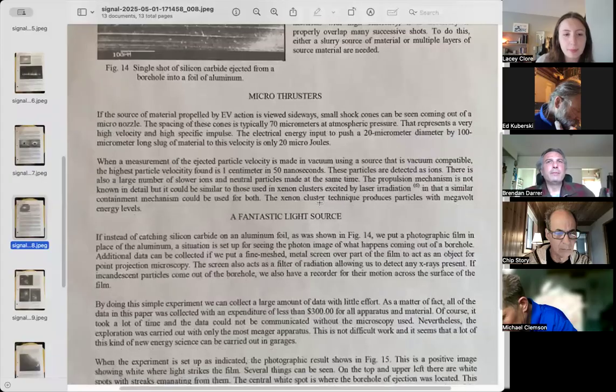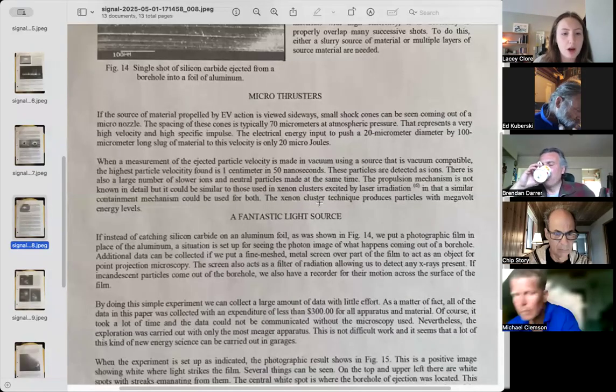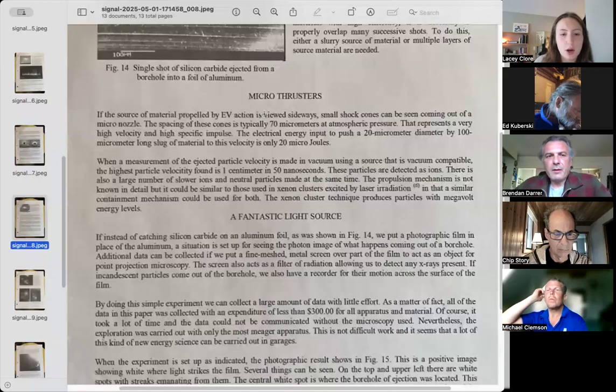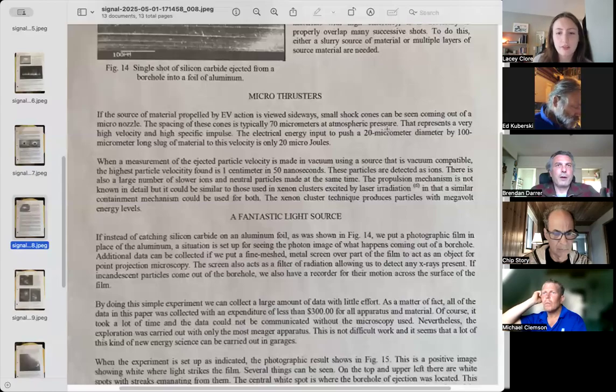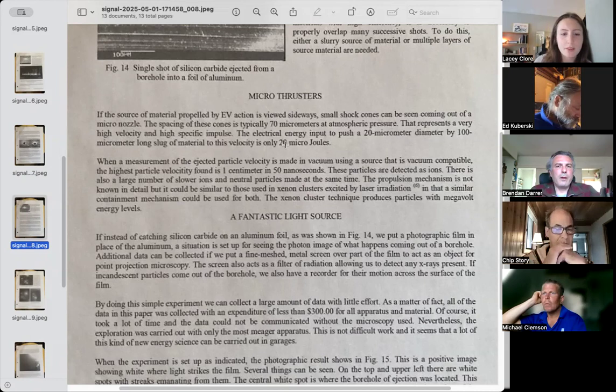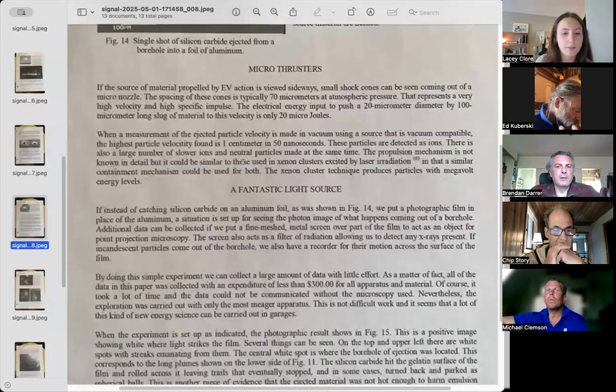Microthrusters. If the source of material propelled by EV action is viewed sideways, a small shock cone can be seen coming out of a micro nozzle. The spacing of these cones is typically 70 micrometers at atmospheric pressure. That represents a very high velocity and high specific impulse. The electrical energy input to push a 20 micrometer diameter by 100 micrometer long slug of material to this velocity is only 20 microjoules.